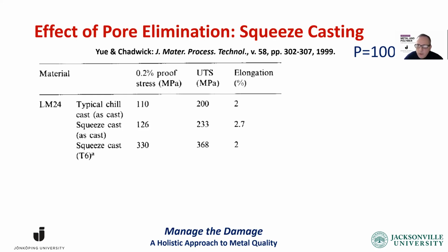What's wrong with that? We're used to 1%. 2% is not bad. Okay, let's put that into perspective. The maximum ductility potential of the alloy at that yield strength is 29, 28, and 15% respectively. And when we calculate the quality index, it goes from 7 to 10. So when we apply 100 megapascal of pressure, we go from 7% quality index to 10%, an increase of 3%.